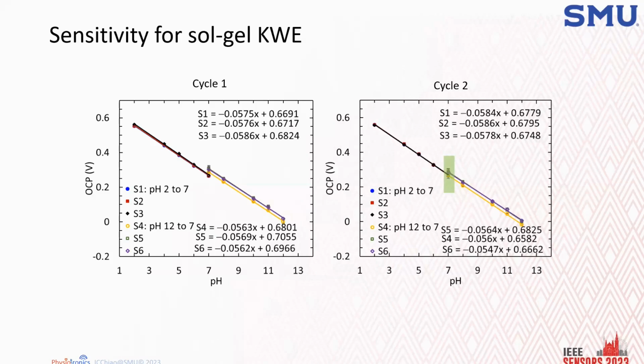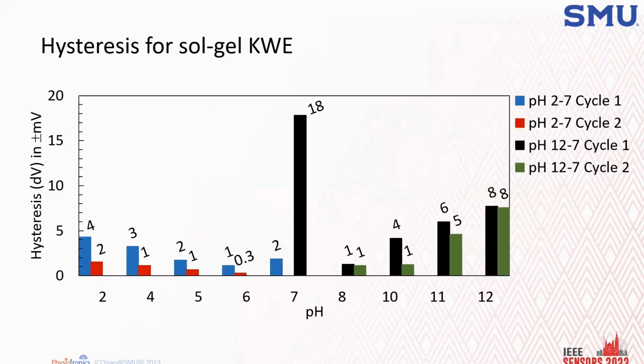However, we do see a little bit of difference there, and we counted that as a hysteresis. So doing that, we collect the hysteresis information. The blue one and the black one are cycle 1, the red one and the green one are cycle 2. Then we found that in the first cycle, even at pH 7, there is a huge hysteresis. That means that when you compare 7 to 7, there's a difference of the potential. But after the second cycle, all this hysteresis disappears. So again, we believe that solving the drifting issue also solved the hysteresis issue.